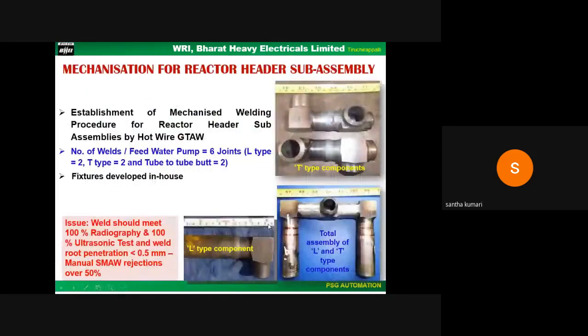This is another successful establishment of a mechanized welding procedure for the reactor header subassembly for nuclear steam generators. This is another significant development made in the recent past. The weld should meet 100% radiography and 100% ultrasonic test, and the weld root penetration should be less than 0.5 mm. With the manual SMAW process, the rejections were over 50%. Earlier, they were also using inserts for the root pass. Now, with this automation, the necessity to use the insert for the root pass has been eliminated.